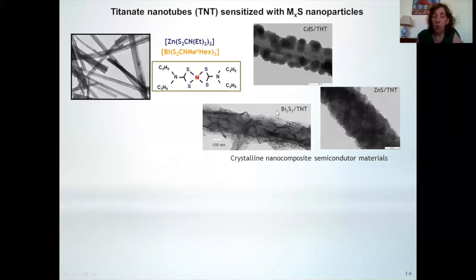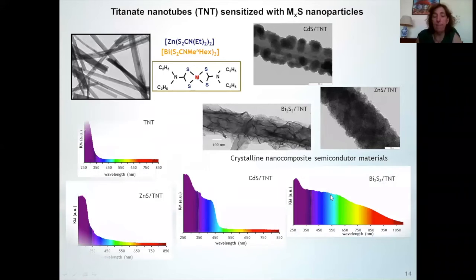Why are these so important for us? Well, we are interested in the optical behavior of these materials. And as you can see here, when we use bismuth sulfide, this one here, we start to have absorption in all the visible range of the spectrum. Also, bismuth sulfide is an excellent adsorbent for cationic species, if we are interested in this point. For the CdS, it's perfect.